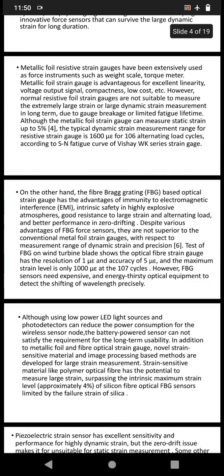On the other hand, the fiber Bragg grating (FBG) based optical strain gauge has the advantages of immunity to electromagnetic interference (EMI), intrinsic safety in highly explosive atmospheres, good resistance to large strain and alternating load, and better performance in zero drifting. Despite various advantages of FBG sensors, they are not superior to the conventional metal foil strain gauges with respect to measurement range of dynamic strain. A precision test of FBG on wind turbine blade shows the optical fiber strain gauge has a resolution of 1 and accuracy of 5, and the maximum strain level is only 1000 at the 10^7 cycles.